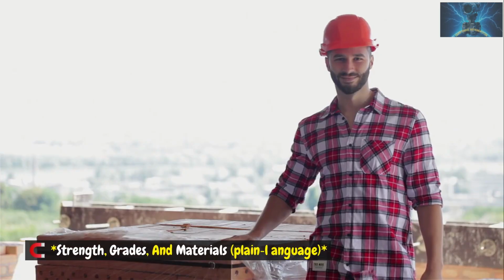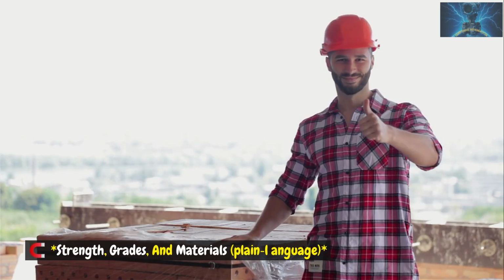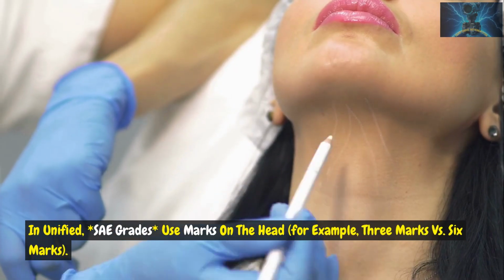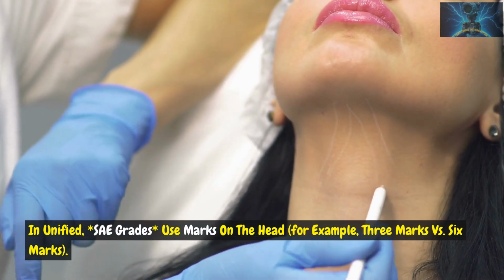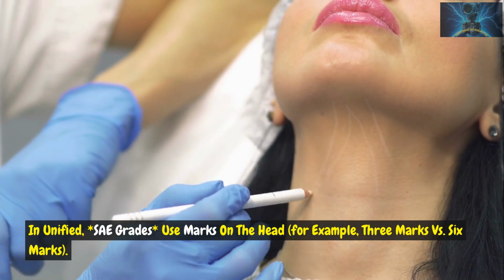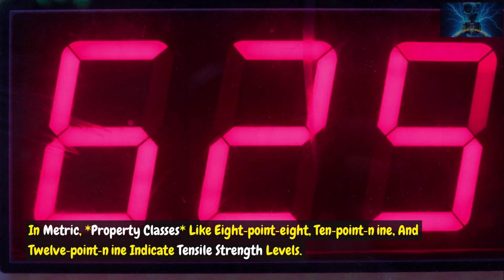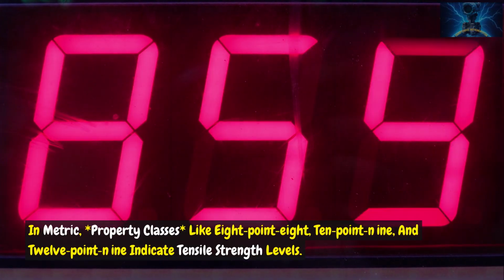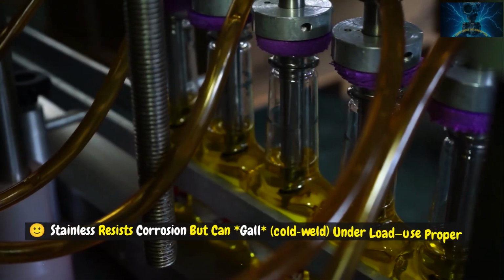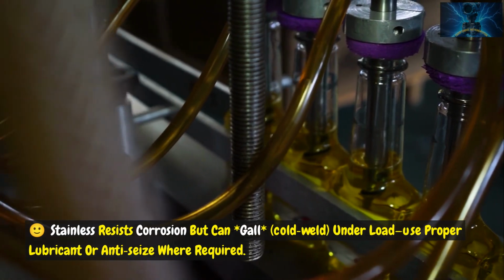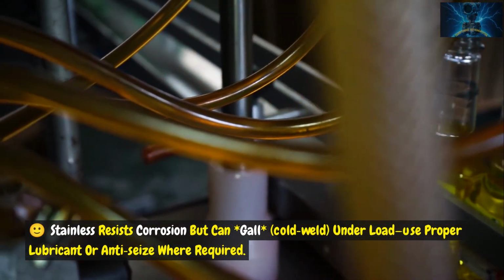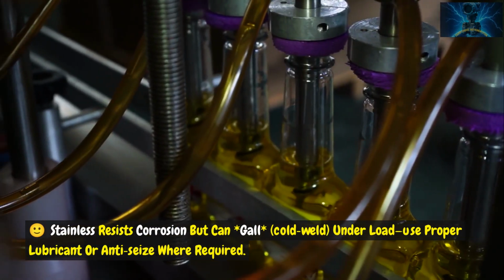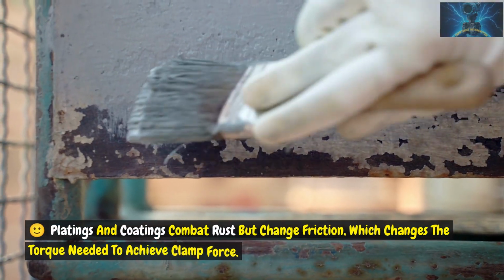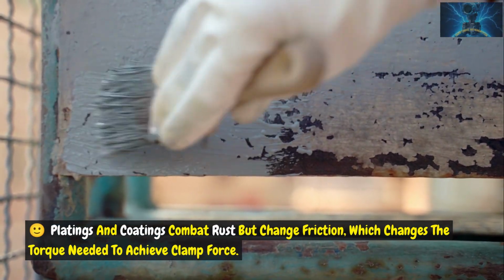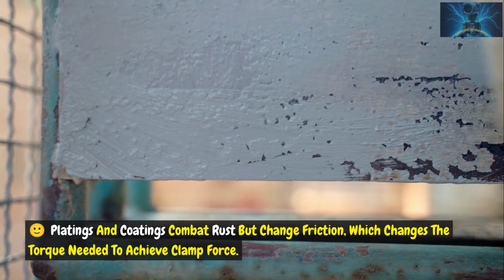Strength, grades, and materials, in plain language. In unified, SAE grades use marks on the head, for example, 3 marks versus 6 marks. In metric, property classes like 8.8, 10.9, and 12.9 indicate tensile strength levels. Stainless resists corrosion but can gall, or cold weld, under load. Use proper lubricant or anti-seize where required. Platings and coatings combat rust but change friction, which changes the torque needed to achieve clamp force.